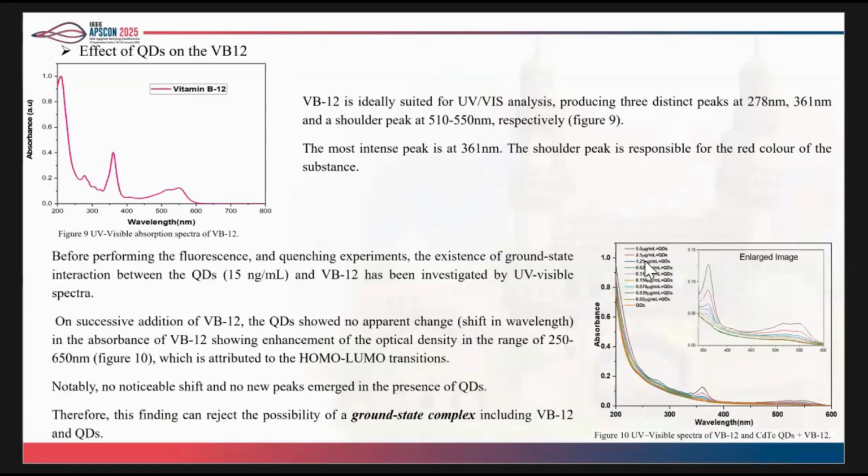Before starting the fluorescence quenching experiments, the absorption spectra were taken for the fixed concentration of quantum dot, varying the vitamin B12, to see whether there is ground state complex formation. From the results we found that there was no new peak, and therefore we can reject the possibility of ground state complex.